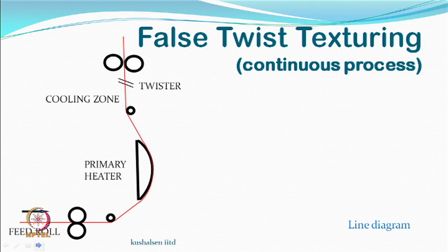So, you are not wanting to wash off all the memory, but only part of it, and you get set in a new configuration, which now percentage wise will be able to stretch only this much, right, and so reduced stretch. So, by using a Helanca process, we are able to get modified stretch yarns, all right. How much stretch again depends on how much winding tension.